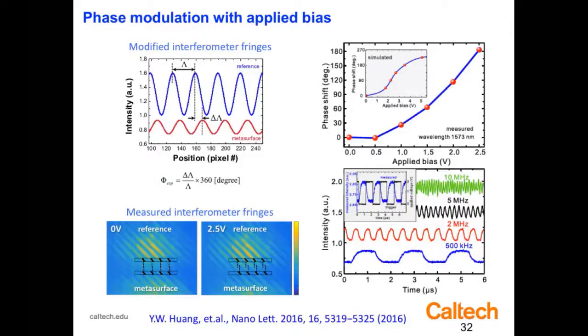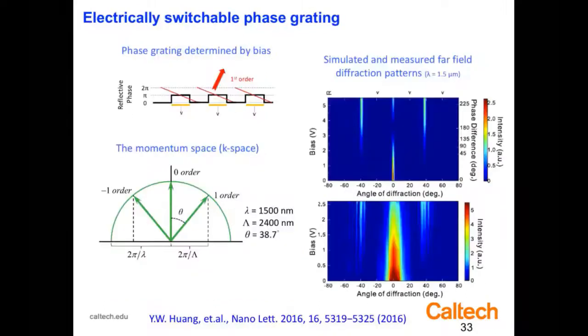So you can actually scan these at very, very high frequencies, and you can make these act as beam scanning devices that can image, and using pulsed echolocation, map out three-dimensional images of structures. And we actually showed that this works by making a tunable diffraction grating. This is the experiment and the theory.